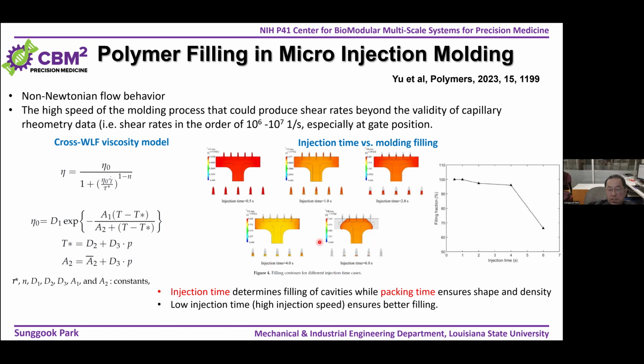Okay, so actually what you can see is as you increase the injection time, meaning the lower the shear rates, the filling basically becomes worse. Okay, and that is associated with the shear thinning behavior of most of the polymers used for injection molding. So as you increase the shear rate, as you shorten the injection time, the viscosity becomes smaller. Okay, so basically you prefer a high injection speed over a low injection speed for better filling of your molten polymers into the micro and nanoscale cavities in injection molding.